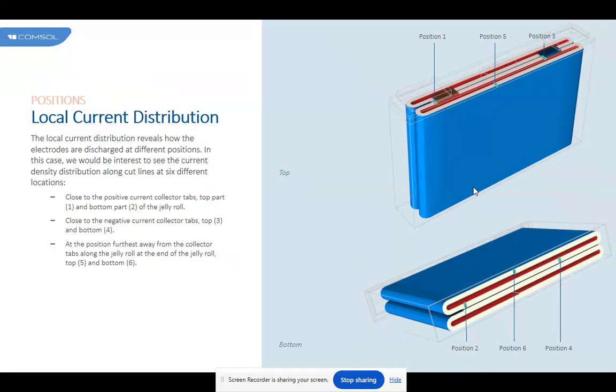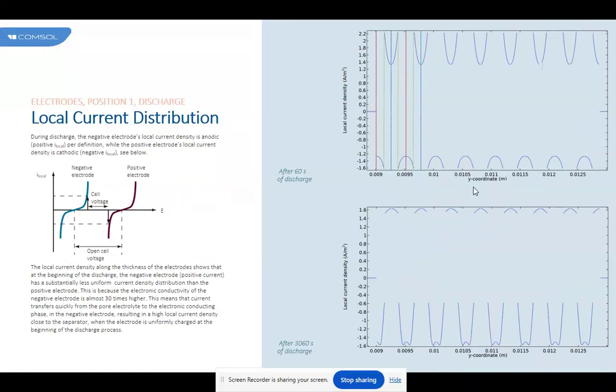The local current distribution reveals how the electrodes are discharged at different positions. In this case, we would be interested to see the current density distribution along cut lines at six different locations: close to the positive current collector's tabs, top part and bottom part of the jelly roll; close to the negative current collector tabs, top and bottom; and at a position further away from the collector tabs along the jelly roll, at the end of the jelly roll, top and bottom.